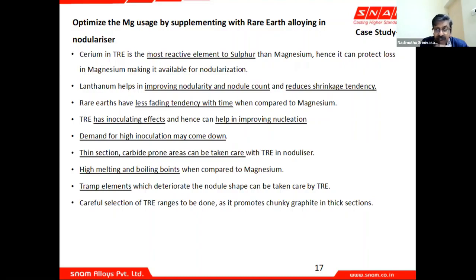When you add these elements into your molten metal, the first sulfide formed is cerium sulfide, which is more stable, and it can therefore protect loss of magnesium because cerium reacts with the sulfur, and therefore magnesium is available for nodularization. Lanthanum helps in improving the nodularity and the nodule count, and it has a tendency to reduce the shrinkage tendency.